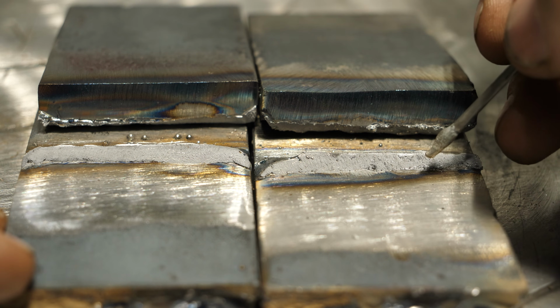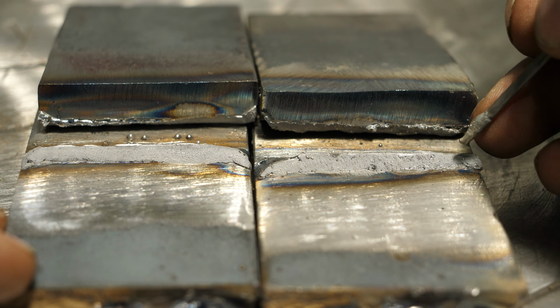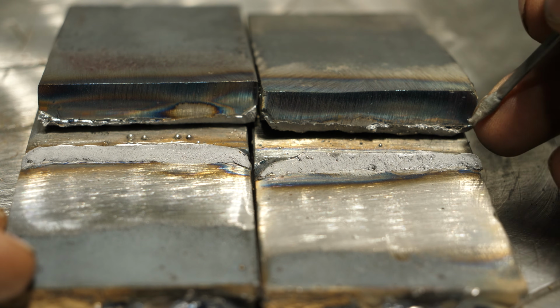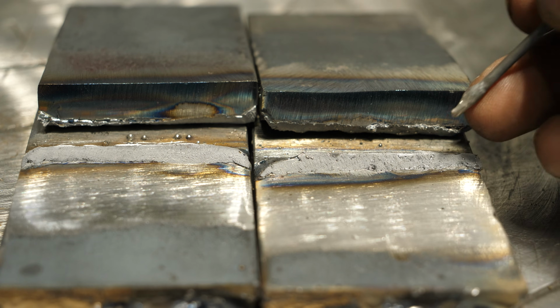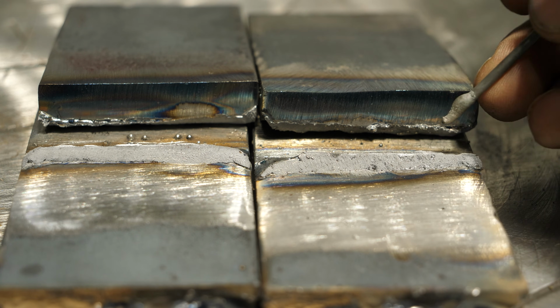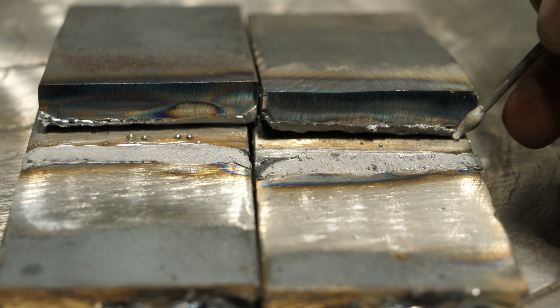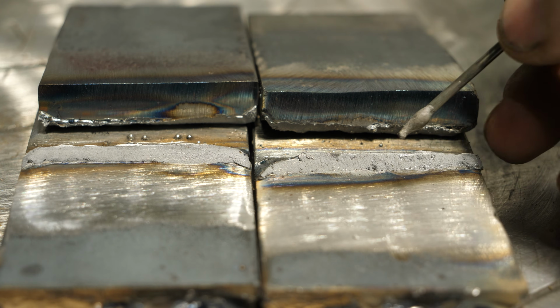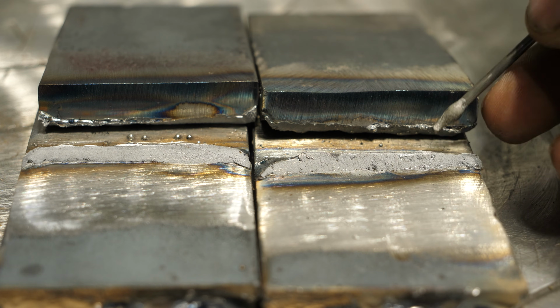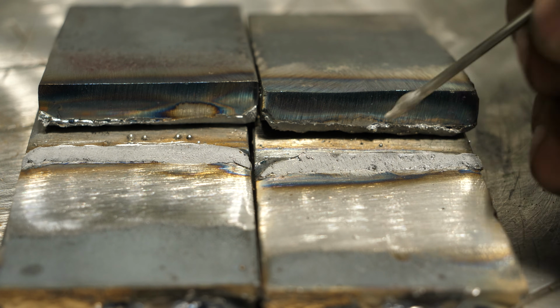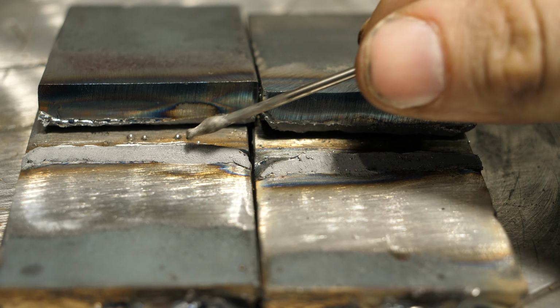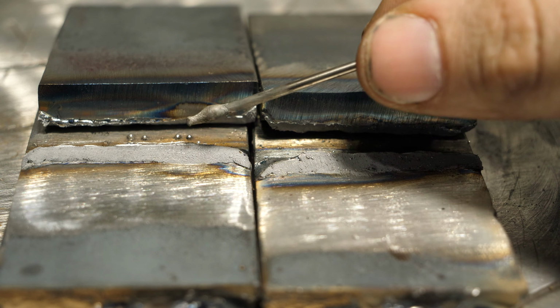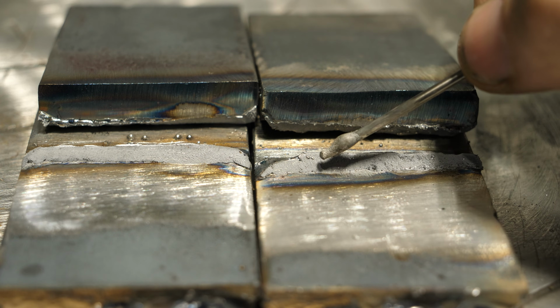I could not dial out the occasional piece of porosity with it, which has been my experience with flux core .035 across the board for all the years I've been using it, is that it really works great on 1/4 inch and thinner, and you're going to occasionally get porosity with it. So contrasting these, back to what we're talking about, cleaner internal weld structure.